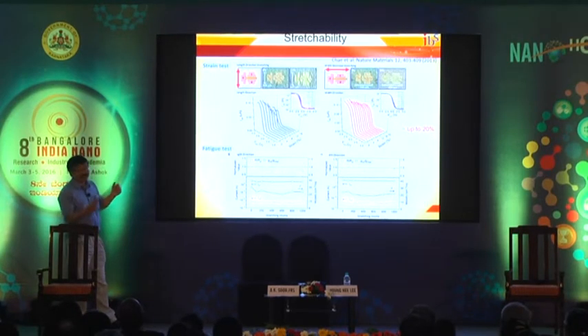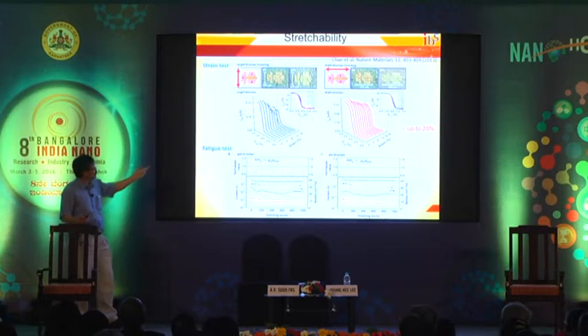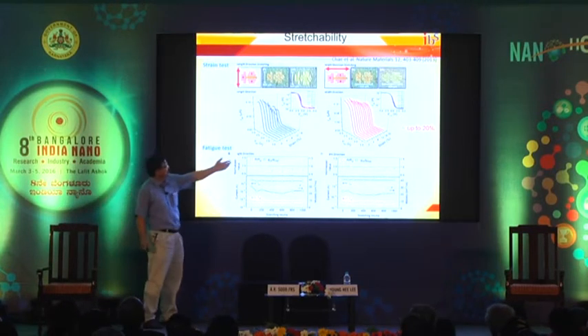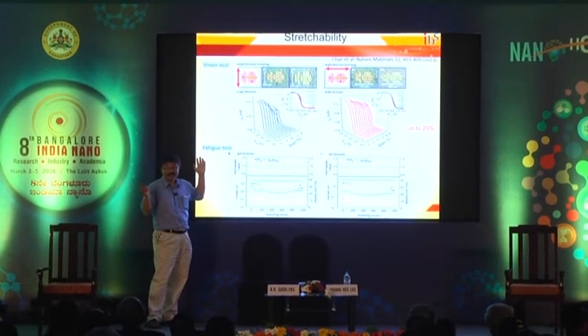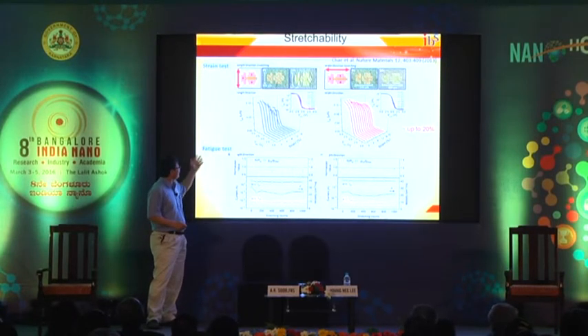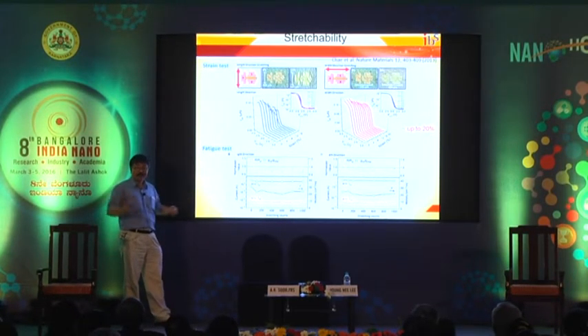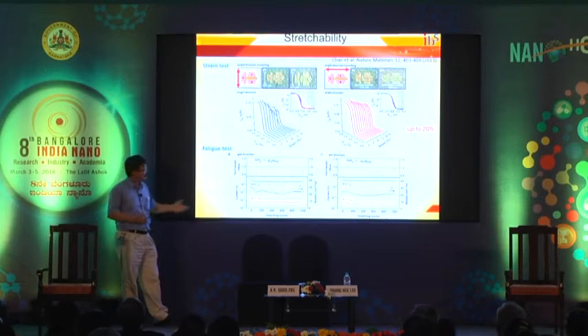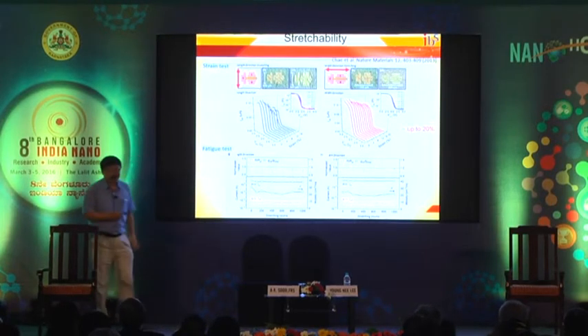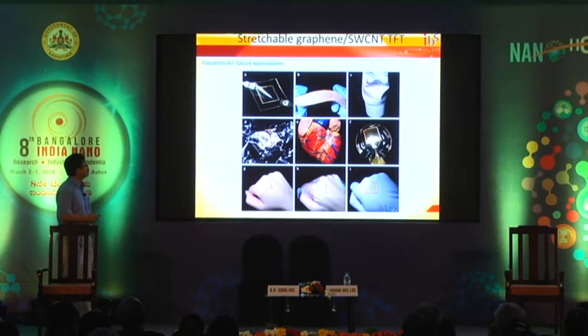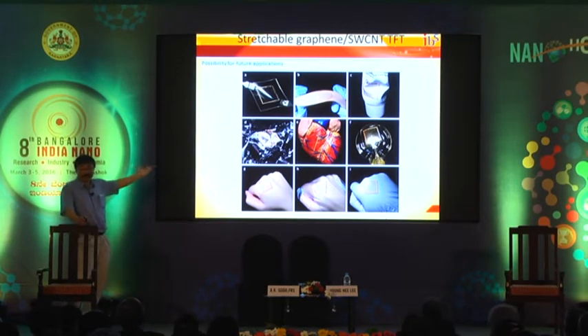Now, when you really stretch them and then you see how the device characteristics work, up to 20% they work perfectly. And if you test this fatigue test, just simply repeating this many, many times, still they're okay. So it's quite robust. So we are quite happy with these results. And you can simply transfer this whole device onto any kind of desired stretchable material, and you can see they are all fine.